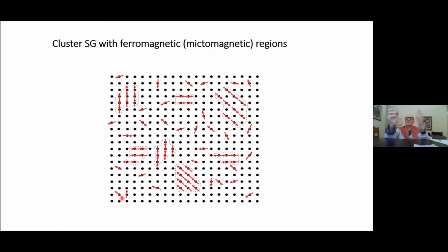So I want to take this array, this random array of spins, which interact over rather long distances. We have the mechanism, and these interact with a probability, depending on the distance, ferromagnetic parallel, antiferromagnetic antiparallel. And this freezes out. So when all these spins become locked in, become frozen at a rather well-defined transition, we have the frozen spin glass state.